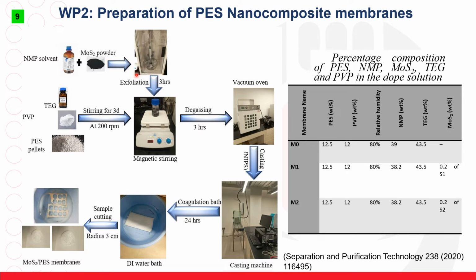We therefore went ahead to blend these powders with polyether sulfone in addition to other additives. For instance, NMP was used as the solvent, whereas PVP was used as the pore former. And the solutions were very viscous, so we took beyond 3 days of mixing.